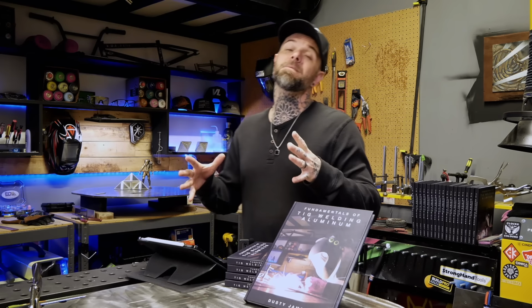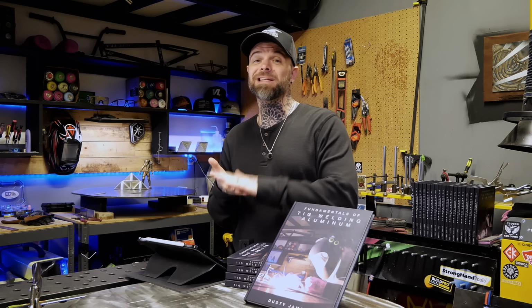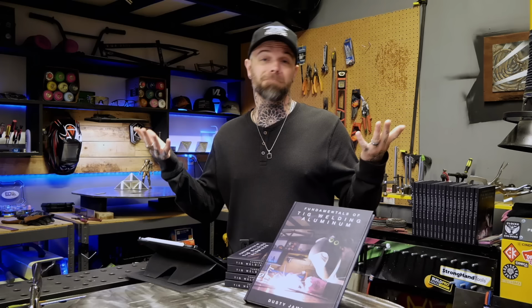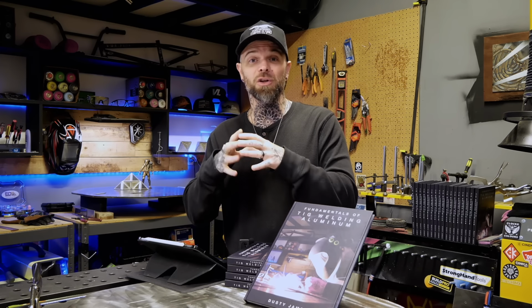When these fundamentals have been done really well and the balance between heat and filler has been balanced really well, the gas literally only has the one job of just shielding your welding puddle. That's it. We have to keep nitrogen and other crap in our atmosphere out of the welding area. This is how we prevent oxidization. You can reach a point where you have so much gas coming out of your torch that it will make your stuff look a little bit shinier, I guess. But proper balance between the heat input and the filler material you are using are things that are actually supposed to do that. The gas is literally just supposed to prevent oxidization.